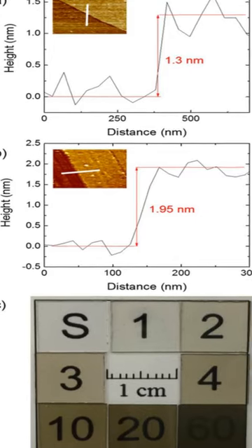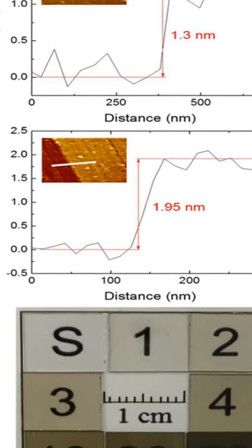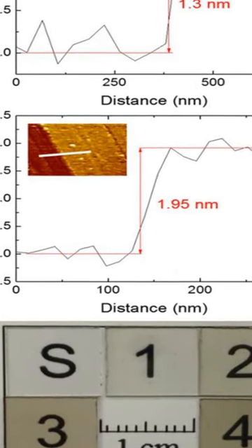The material thus ablated was deposited on a single-crystal sapphire (0001) substrate kept at 700 degrees Celsius in an ambient vacuum of 10^-6 torr.